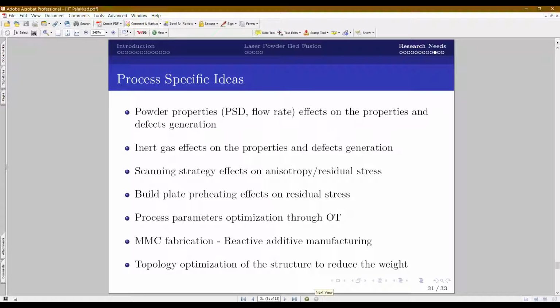One is the powder. As you know well, spherical particles are the ones needed for laser based powder bed fusion, because of the flow rate requirements and the packing density requirements. Similarly, the particle size should be in the range of 15 to 60 micrometer as defined by different companies. So understanding the powder size distribution and shape effects on the properties and the defect formation in the component is important. There are some talks wherein they say even water atomized powder can be used to get similar properties as achieved by the spherical particles. So this area is still a gray area. There is no complete understanding of this.